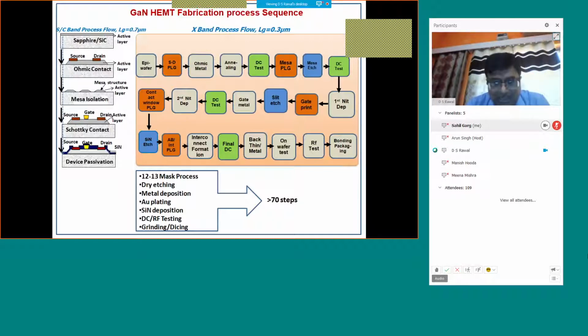So grinding is the process which is used to reduce the thickness once you complete the fabrication on the front side of the wafer. And then, since silicon carbide substrate is involved, once we completely fabricate the devices, we need to separate them by cutting or dicing them. So special dicing techniques are used to separate these devices, because we have to dice the silicon carbide. So all these processes are now available at our place, and we are regularly using them for the fabrication of devices up to X band.